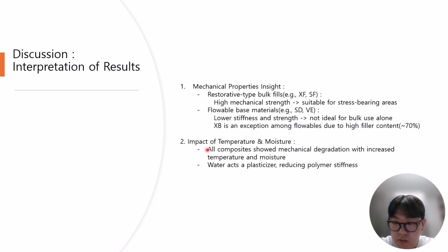Second, on temperature and moisture effects, our composites became weaker as temperature and moisture increased. Water acts like a plasticizer, softening the material and reducing stiffness.